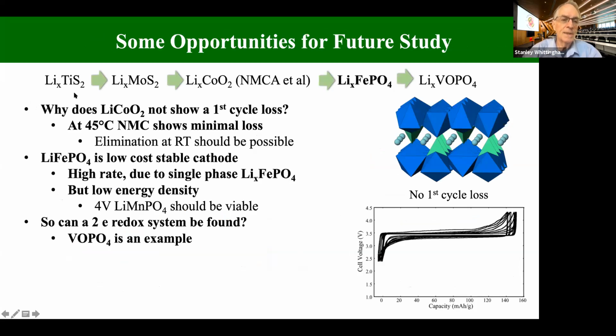I said we started out with titanium disulfide. Moli Energy in British Columbia switched to molybdenum disulfide because this is a naturally occurring ore in British Columbia called molybdenite. They said they made batteries commercially for quite a long time, but had problems with the lithium anode. The field then switched to lithium cobalt oxide, then to NMCA, and then the field moved to lithium iron phosphate for low energy density applications.